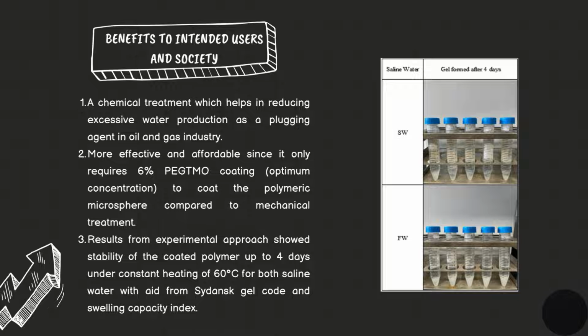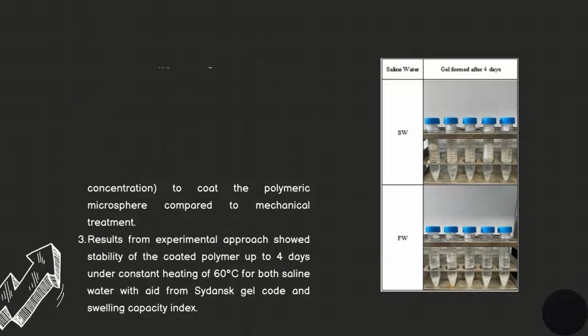And lastly, results from the experimental approach showed stability of the coated polymer up to 4 days under constant heating of 60 Celsius for both saline waters, with aid from the Sydansk gel code and swelling capacity index.